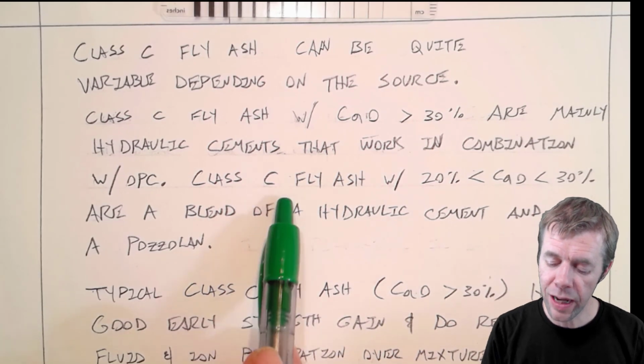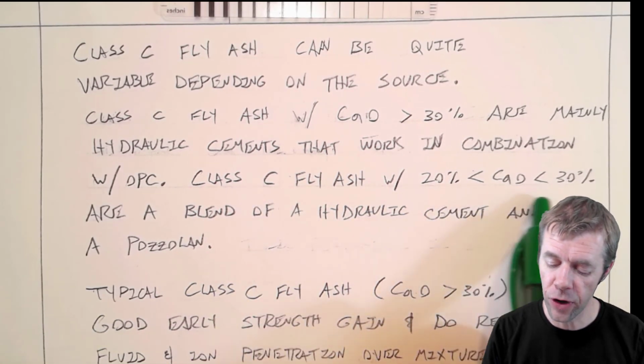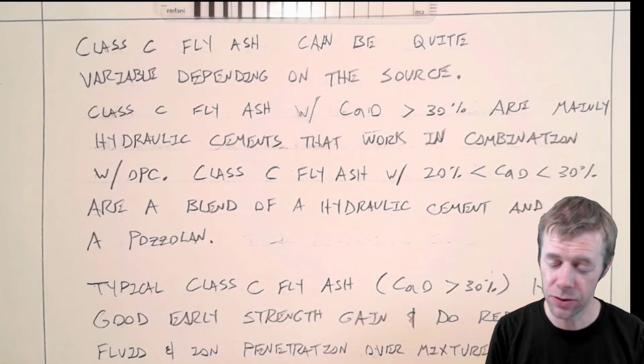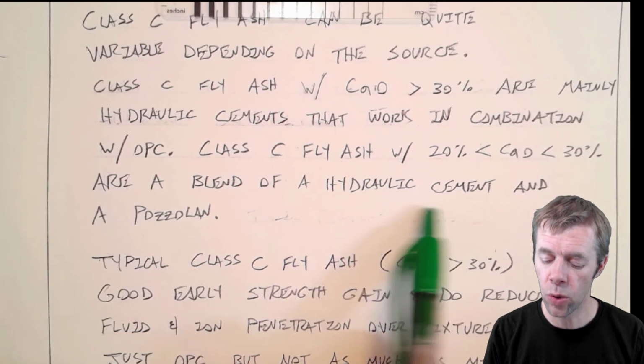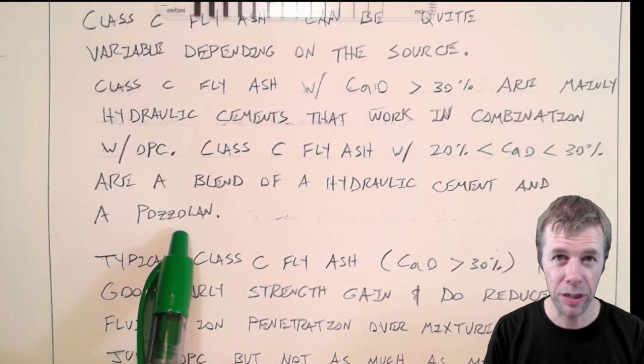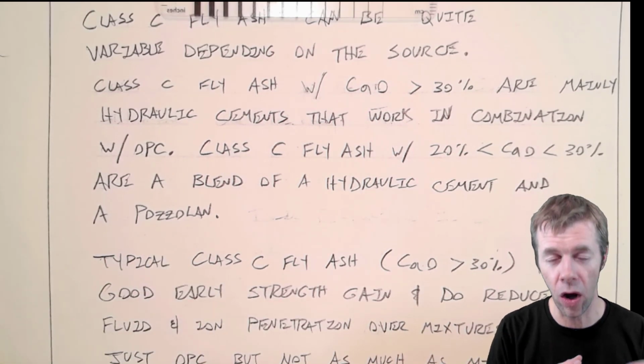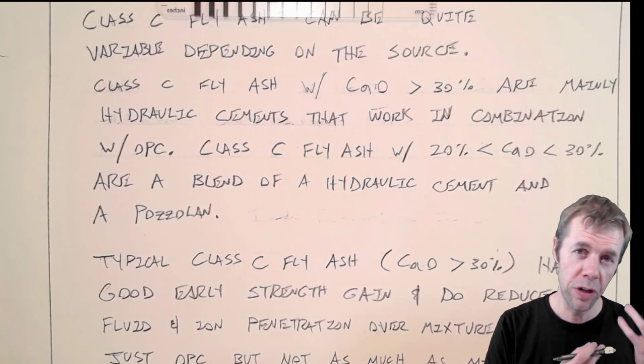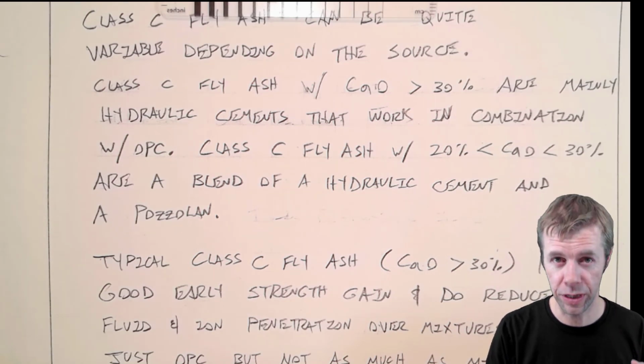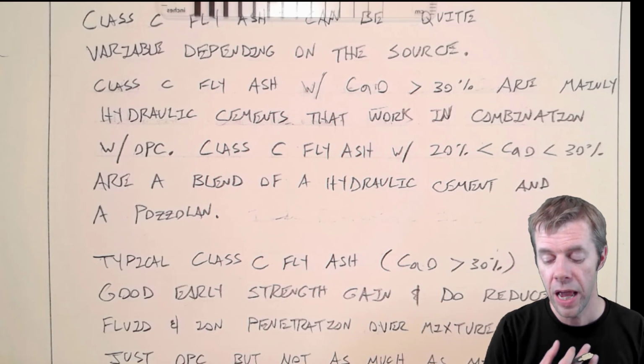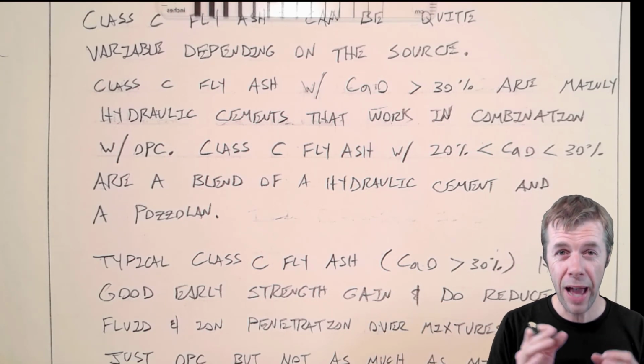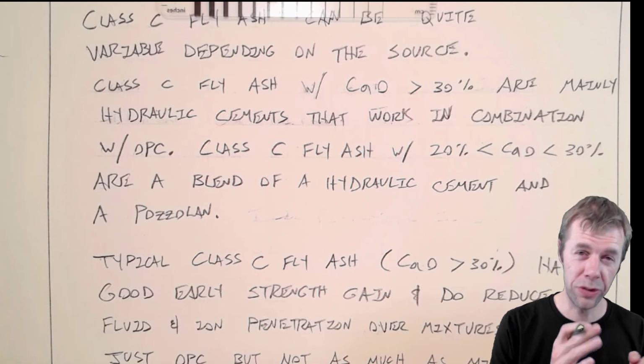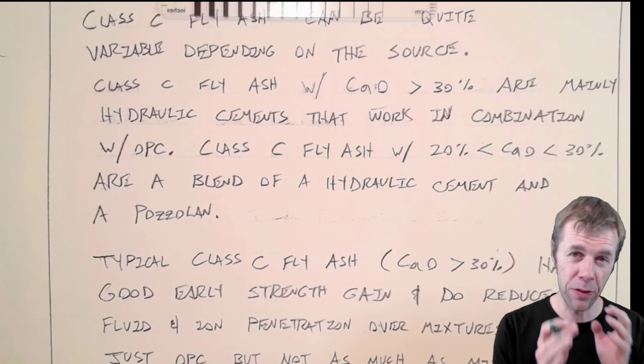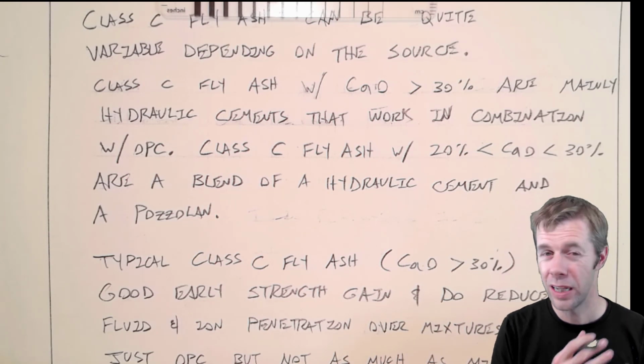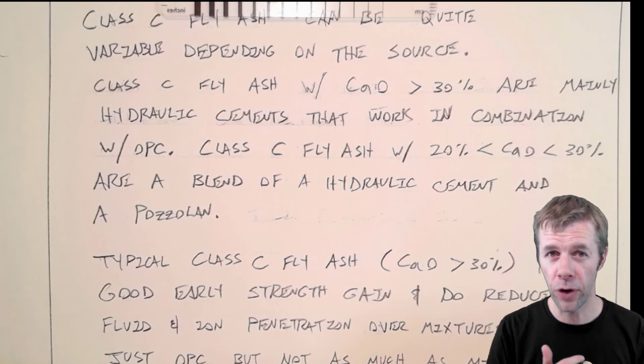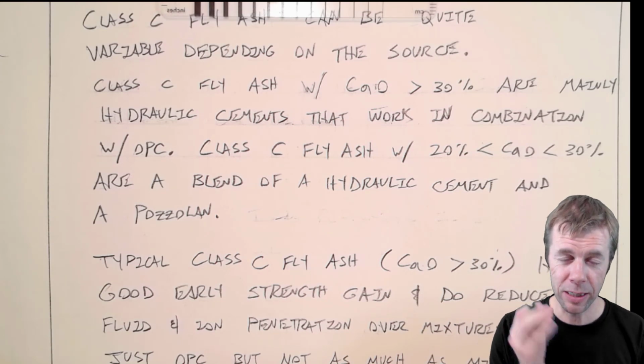These Class C fly ashes that are between 20% and 30%, now, they're interesting beasts. They're partially hydraulic and partially pozzolan. And actually, all fly ashes are this way. All of them have a combination of hydraulic cement characteristics and pozzolanic characteristics. And I guess what I'm trying to say here is that as you get closer to lower calcium, usually it's more pozzolanic. And when you get in this mid-range between 20 and 30%, it's kind of a blend. And if it's greater than 30%, it's mainly a cementitious material.